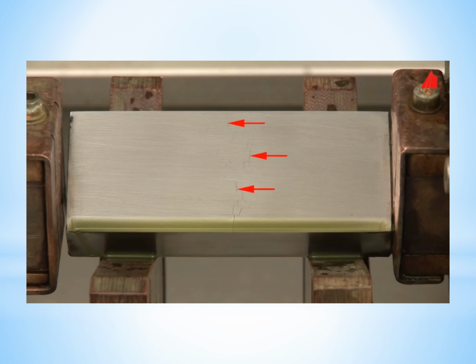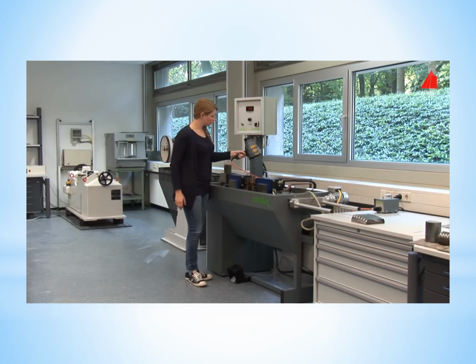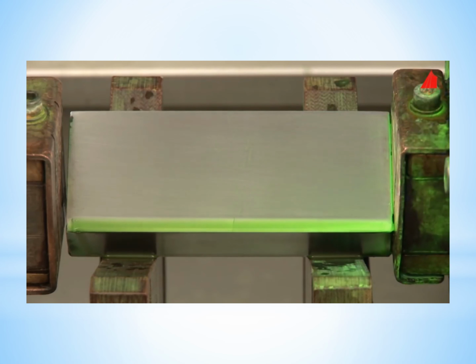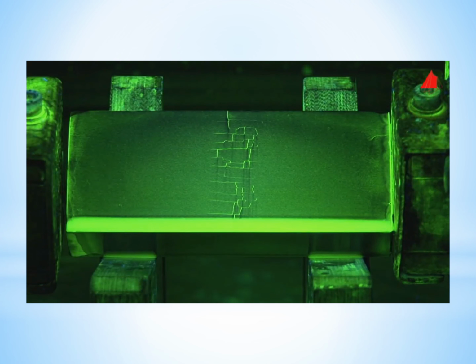Already in daylight, dark lines are visible on the surface. The lines can be seen much better under ultraviolet light and particularly well at darkening the daylight. The suspension contains pigments that cover the magnetic particles and fluoresce under ultraviolet light. The particles run off in areas free from defects and they are attracted and clustered near defects. This workpiece shows a whole array of cracks.